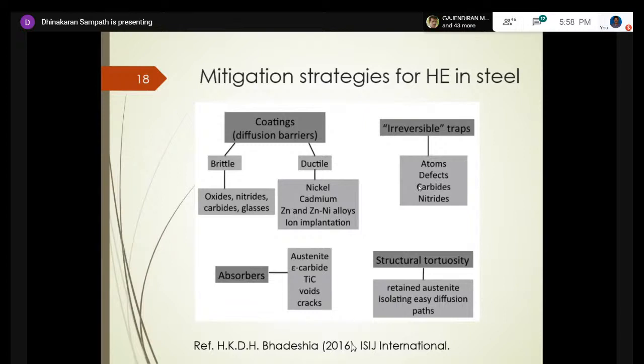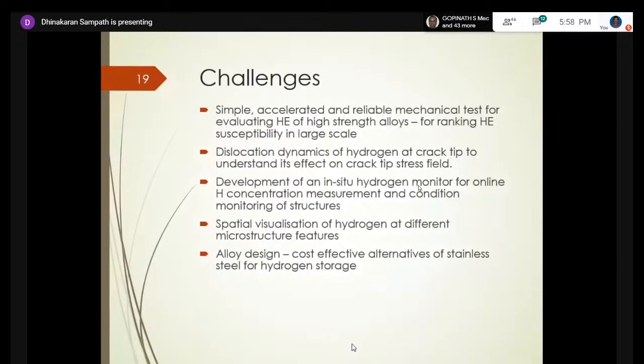So it will not allow hydrogen to go to the crack tip and cause failure. Here I listed some challenges. As I told, for hydrogen embrittlement, fracture mechanics specimens are quite useful. But industry looks for ranking purposes, simple, accelerated and reliable mechanical tests for evaluating hydrogen embrittlement of high strength alloys. This is a good challenge, because people know that fracture mechanics specimens are useful, but still they use low strain rate tests with smooth specimens.